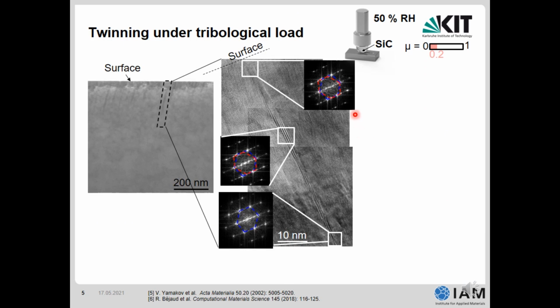So here you can see the high resolution TEM image, which was done at the Institute for Nanotechnology at the KIT. So thanks to my colleague Lakshmi Manta for that. So here is now the surface, and here is the line type characteristic. Here you can see the FFT analysis, and the red dashed line connects the diffraction points for the twin and the blue for the matrix. And now we can see here that this was clearly detected as a twin, and down here there's the twin not anymore.